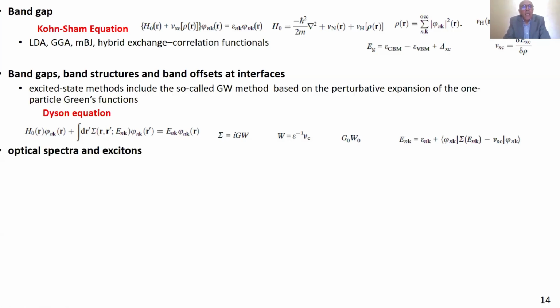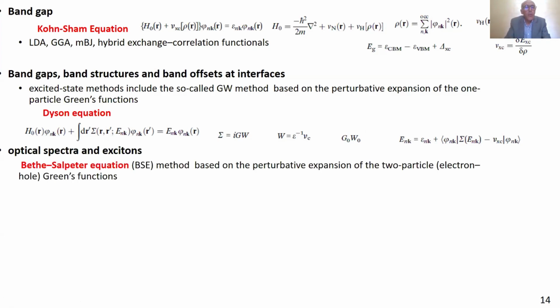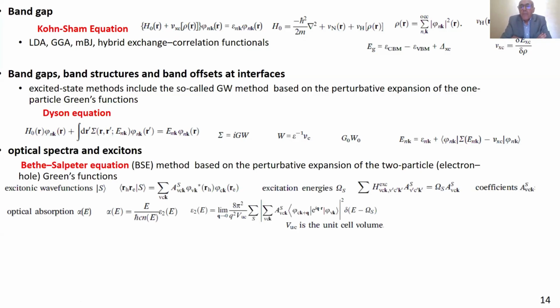If we are interested in optical spectra and exciton, then we have to use a method based on the perturbative expansion of the two-particle Green function, especially electron and hole. This equation is the Bethe-Salpeter equation, and from this equation we can determine the exciton energy and also the exciton wave function and the optical absorption.